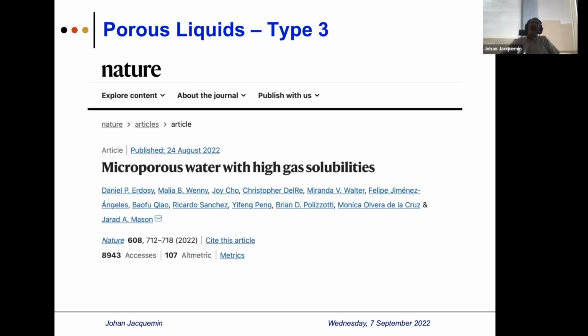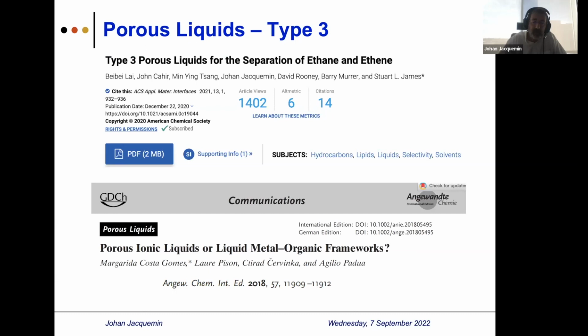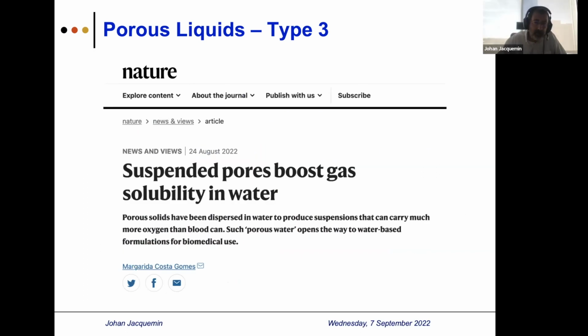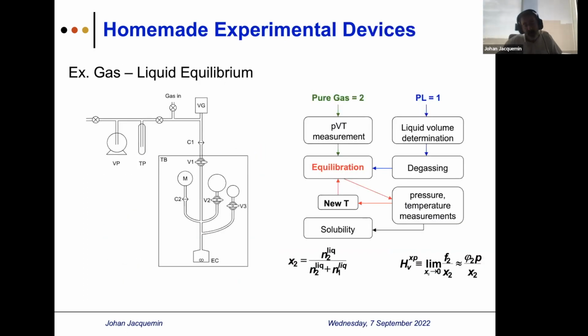And of course, to determine this, we may want to move from homemade equipment to commercially available turnkey equipment. I just want to highlight the technique that we developed, I would say, at Belfast, that I learned from Margarida Costa Gomes's lab in Clermont-Ferrand, and then I developed also in Tours, and now am developing at Mohammed VI Polytechnic University. This technique is really based on the isochoric technique, and it is very, very simple. If you have a porous liquid containing non-volatile solvents, that's very important, you can simply determine the Henry's law constants, or Henry's law volatility, expressed